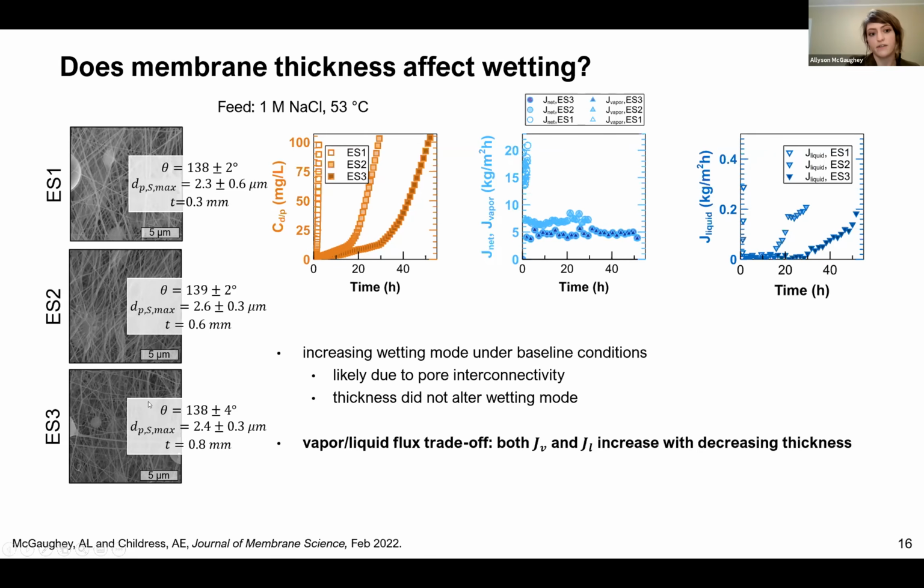I do think that may have affected wetting and potentially opened up larger gaps in the membrane, maybe giving it a larger effective pore size than what we characterized, by providing this large chunk of polymer material but opening up gaps potentially below it or around it. So that's not something we looked at, but it's a really good point. So thank you for that.